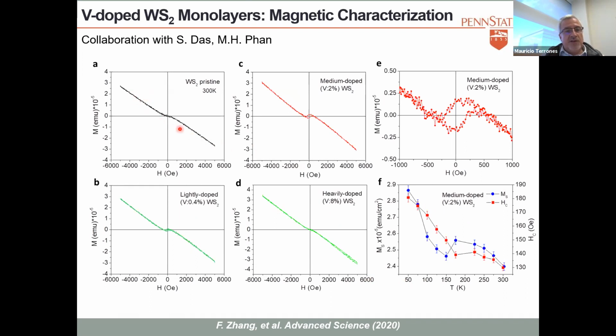So this is a diamagnetic signal, right, that we are recording. We are not subtracting anything because we want to see the signal as it is. And then when you have 0.4, you have a little bit of this hysteresis loop. When you have 2%, you have increased the ferromagnetic signal. And when you put 8%, it sort of decays again. So something is happening, right?